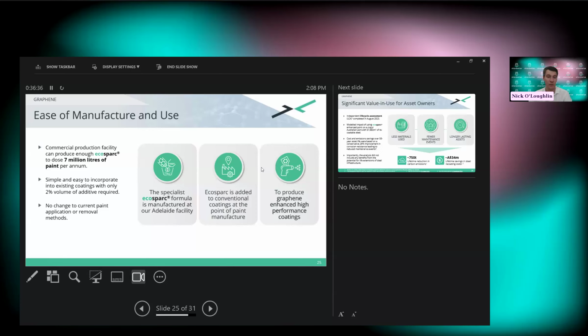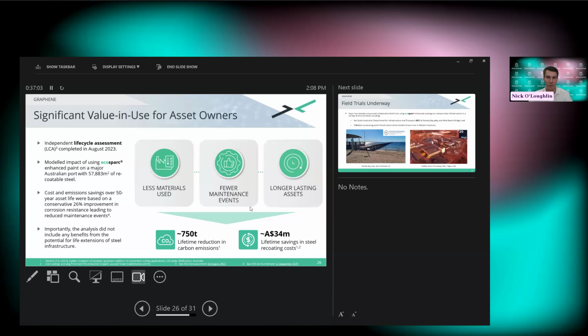We've got a commercial manufacturing facility for this additive based in Adelaide, and we can dose up to 7 million litres of paint, which is quite a lot in the Australian context, but a drop in the ocean globally. One of the reasons we're able to dose so much paint is that the additive is only added at 2% by volume. So, quite small amounts per litre of paint, which means that we can have a big impact for not a lot of material. Why this is important and why we think that it should and will be adopted by the market is the significant savings, both in terms of cost and carbon emissions, that it can yield for asset owners.